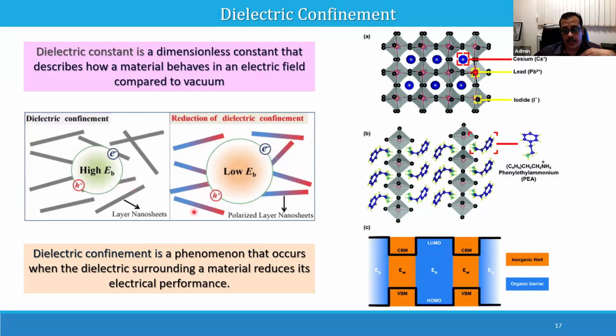But on the other hand, in the lead-based material, the exciton binding energy is low. You can easily separate the electron and hole. You can see it is already well separated, and so by simply giving a small bias voltage, you can easily separate them into electron and hole. Of course, we cannot bring back lead. So what can we do with our bismuth or tin-based material? So instead of using a simple organic cation, we slightly improvised.